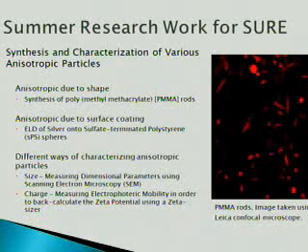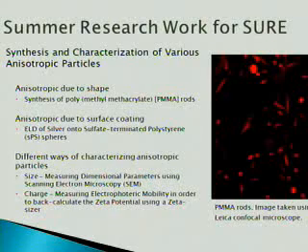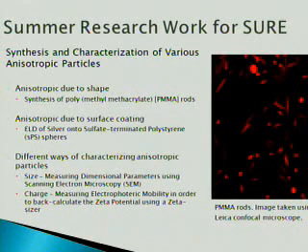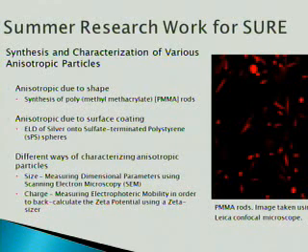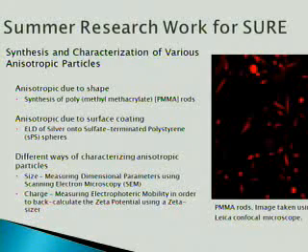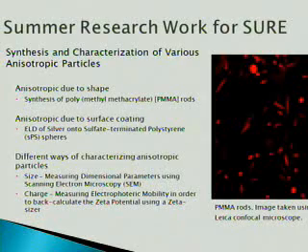I've also been characterizing these particles. The two main ways to characterize them are with regards to their size, which I've done by measuring dimensional parameters using the scanning electron microscope. I've also been analyzing charge, using a zetasizer machine to obtain the electrophoretic mobility, and using this to back-calculate the zeta potential of the colloidal system.